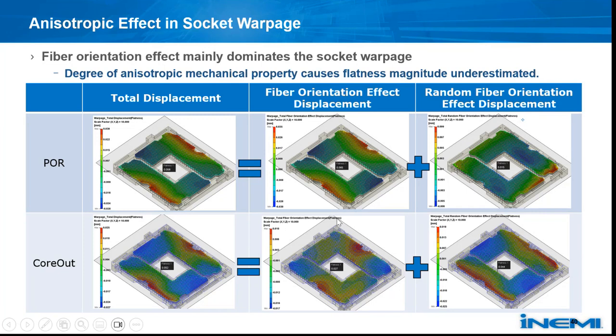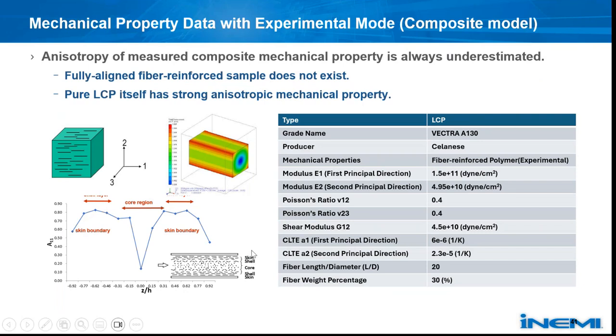Next page. So why does the input by composite model underestimate the anisotropy of plastic? The benefit of input by composite model is that the material can easily be characterized by measuring the molded sample. However, we know that the fiber in the molded sample is highly aligned near the surface, but more random in the middle of the thickness. Inputting the measured data from the sample as fully aligned data will always cause the underestimate of the anisotropic effect for the simulation.